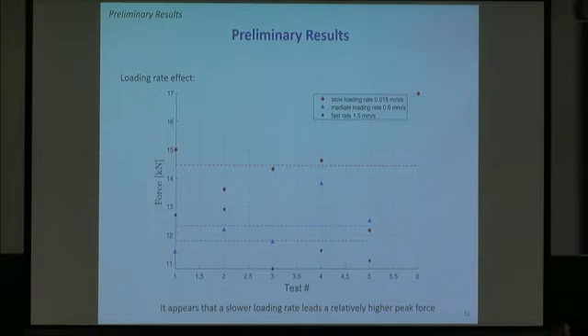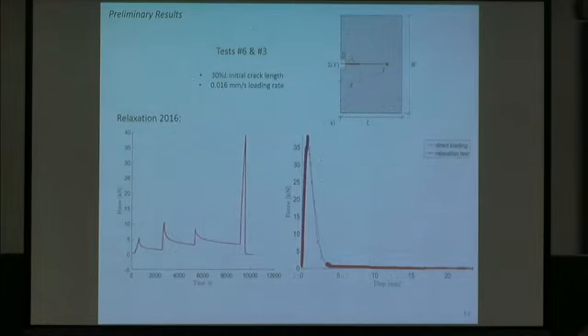It's like this relaxation. And we go through several cycles of such relaxation tests, and we wonder, after so many cycles of relaxation, how would this affect our peak force? Very surprisingly, no influence.